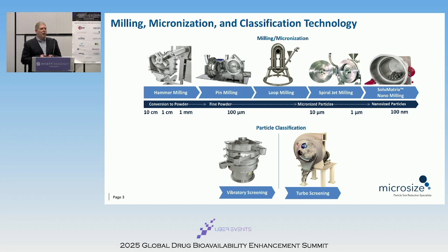Loop mills are lower energy mills compared to a spiral jet. You have just the bottom zone of the mill that does the micronization, and the rest of the loop provides a gentle classification, as opposed to a spiral jet mill, where you have a ring of air all around, and it creates particle and particle collisions uniformly. And then typically with a loop mill, you're around 100 microns on the D90. A spiral jet mill, you can get under 10 microns. Most cases, we can get under 5 microns to support inhaled formulation products.